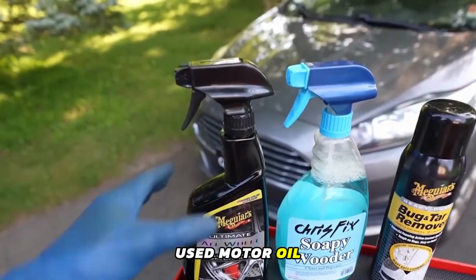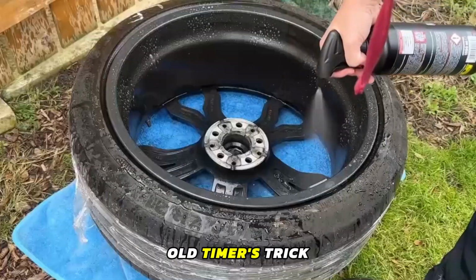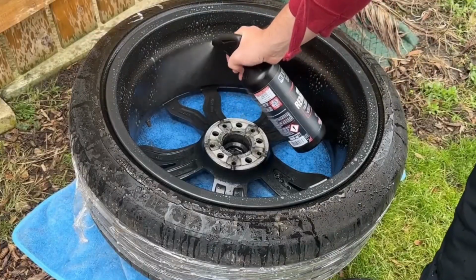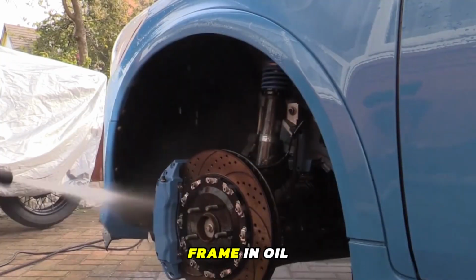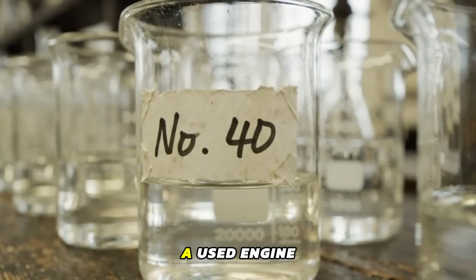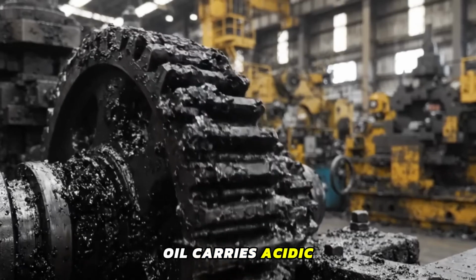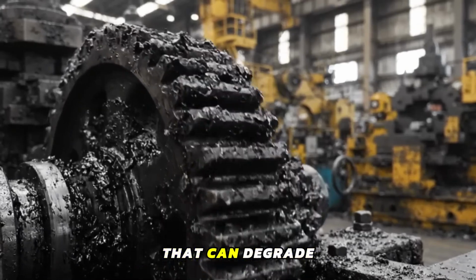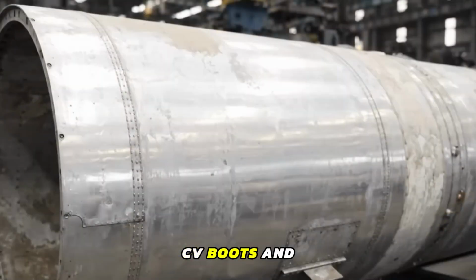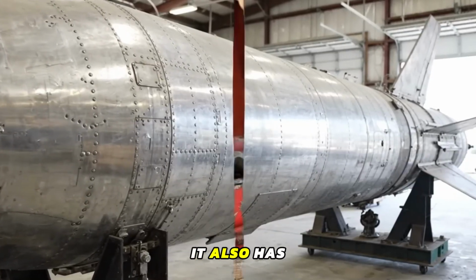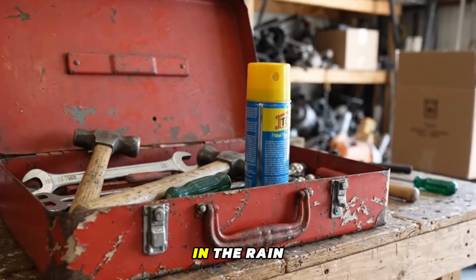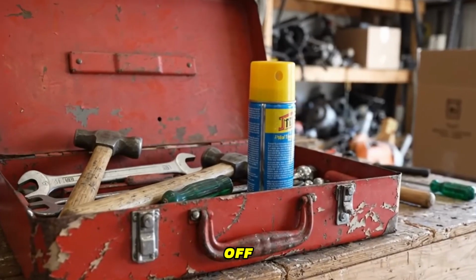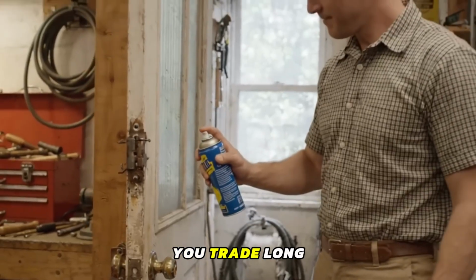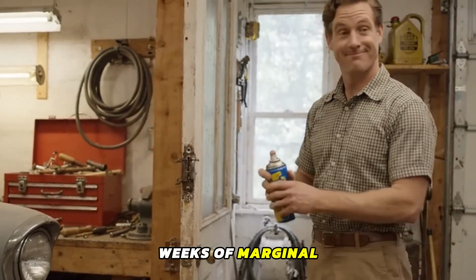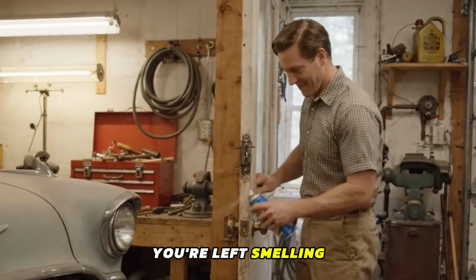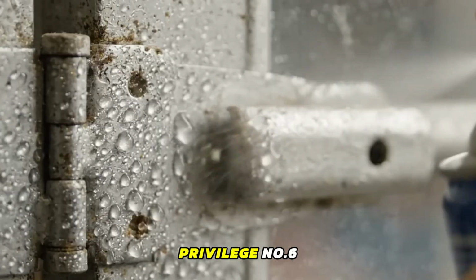Spraying used motor oil underneath the car. This one's an old-timer's trick, and it sounds almost reasonable. Oil repels water, so coat the frame in oil. The reality is messier. Used engine oil carries acidic combustion byproducts and metal particulates that can degrade rubber bushings, CV boots, and brake lines on contact. It also has zero staying power. A few miles in the rain and highway spray washes it straight off the spots that take the most abuse. You trade long-term suspension health for a few weeks of marginal, uneven coverage, and you're left smelling like a quick lube for the privilege. Number 6.